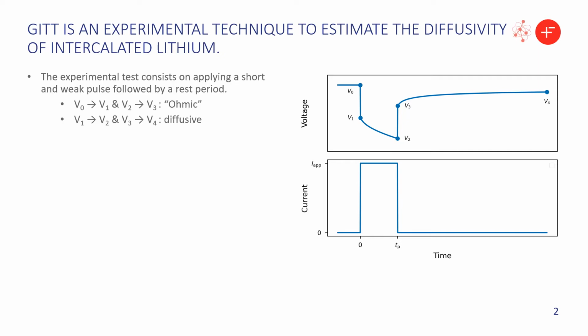And in terms of the voltage response you observe, well, there is some ohmic part. It's not actually quite ohmic. There might be some very, very quick transients, but we assume here it's purely ohmic. And then some diffusive part, and this diffusive part is caused by the change in the open circuit potential caused by the diffusion of lithium inside of the particles. And that's what's going to give us information to obtain the diffusion coefficient.